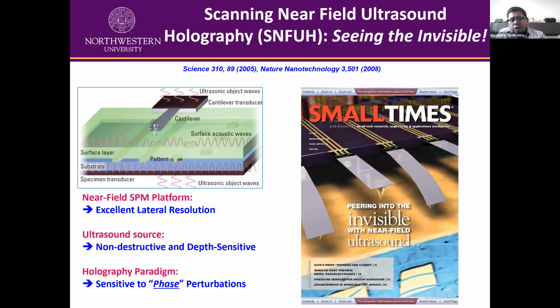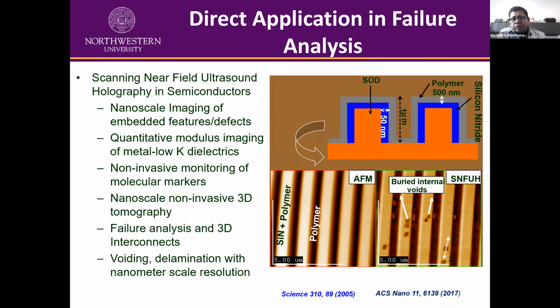And then we have used this for different metal interconnects. On the right side, these are different metal interconnects with different heights, different layers. Then you can see the left side is a pretty decent topography image. On the right side, you can see these different buried internal voids. So if you have cracks or voids at the interface of the metal and the substrate, you cannot detect them in topography, but you can detect them with these techniques. Okay, so this technique is available here. And this is one of the nicest techniques to measure subsurface structures. Now we have seen things down to a few nanometers.